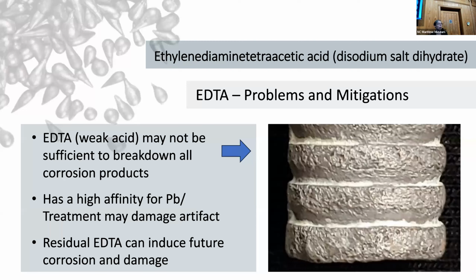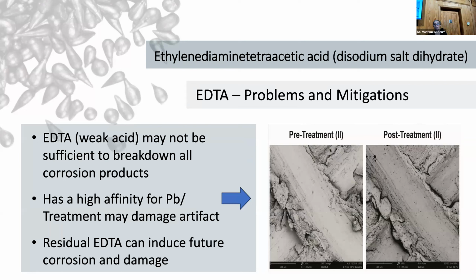However, it had already been there for 2 hours. Most of the surface was exposed. I didn't want to overexpose it, which is why I chose to remove it from solution at the time that I did. But these products are still persistent there. This is an example from a study I did on EDTA treatments like 6 years ago, where you can see the surface changes between before the treatment and after the treatment.